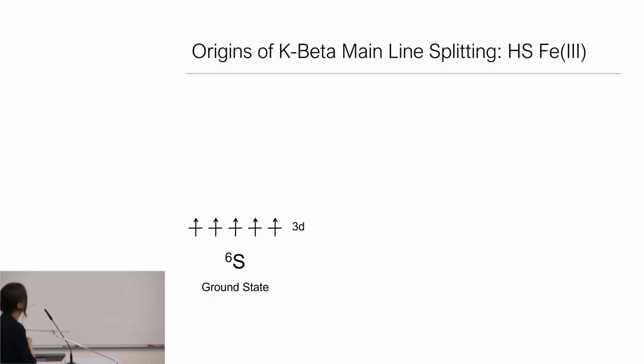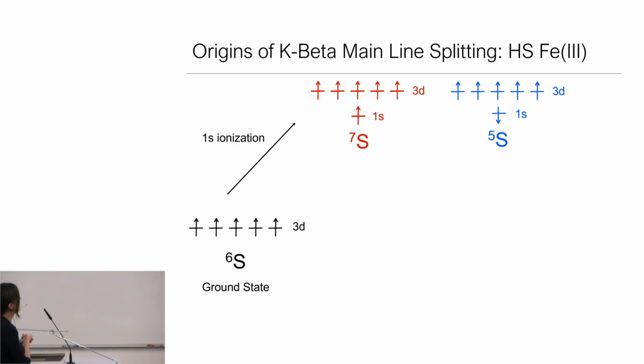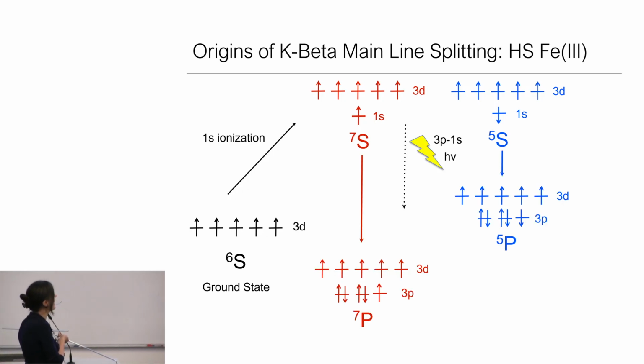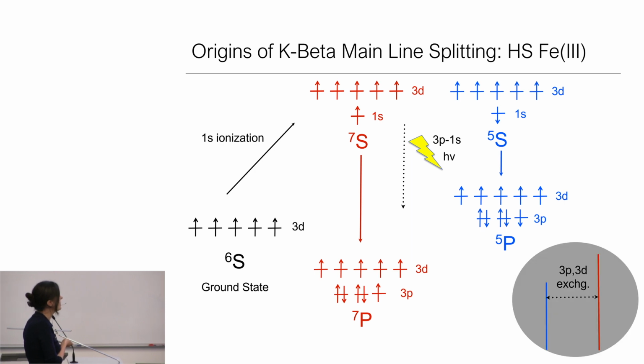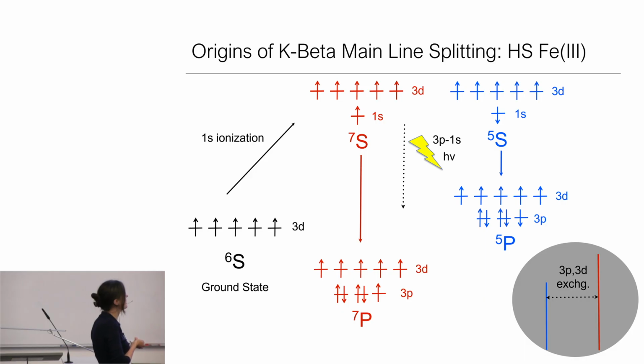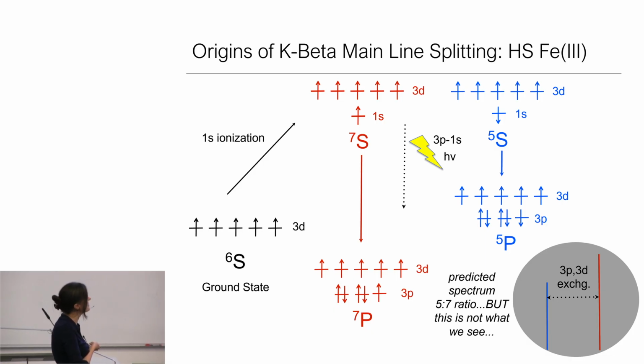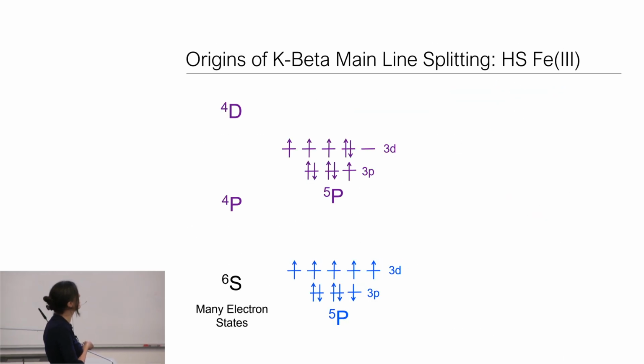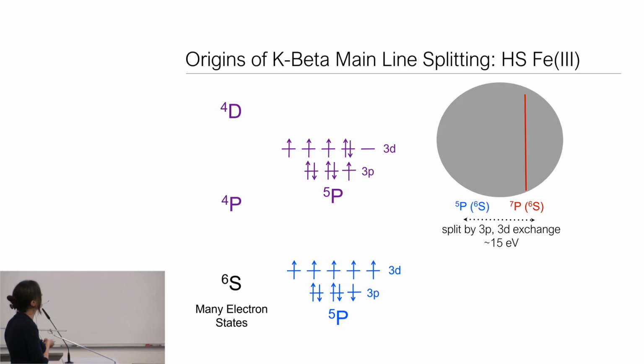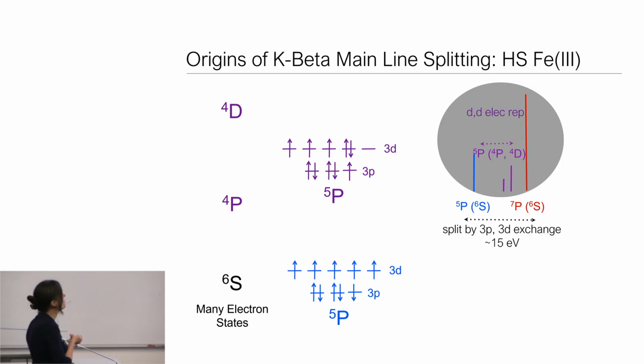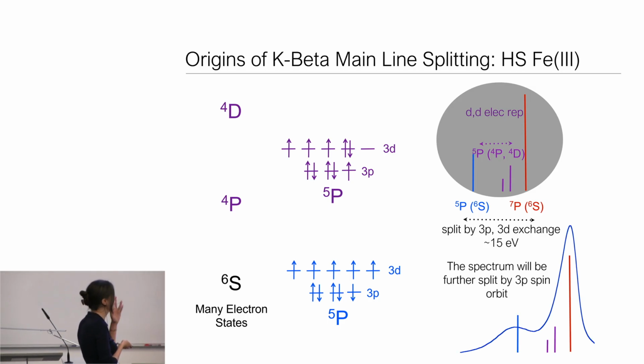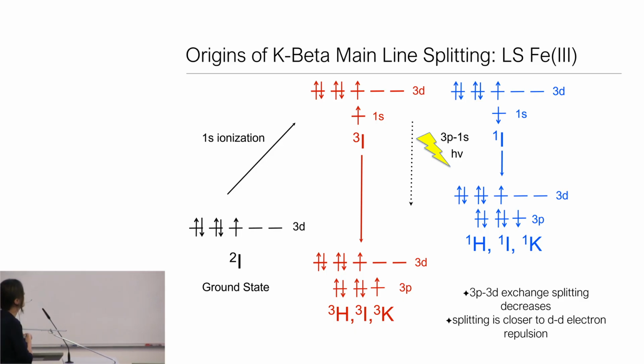So we already did this assignment, but your high spin iron 3, of course, it has this sextet S ground state. And when we actually ionize a 1s electron, that electron can be alpha or beta, giving rise to local septet and quintet S states. It can then relax, and I have final states that are quintet P and septet P. And so in a very simple picture, I should have a final state quintet and septet split by the 3p 3d exchange. As you guys know, there's a full Tanabe-Sugano diagram of low-lying excited states, and so this isn't exactly what we see because we can get a redistribution through symmetry among any of the low-lying allowed excited states, and so the final spectrum looks a little bit closer to this. But these are kind of fun spectra that you can largely understand in a pretty simple pen and paper model. And I won't go through this in the interest of time, but we could do the same thing in the low spin limit.